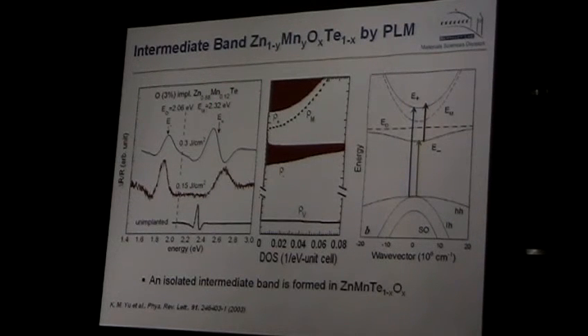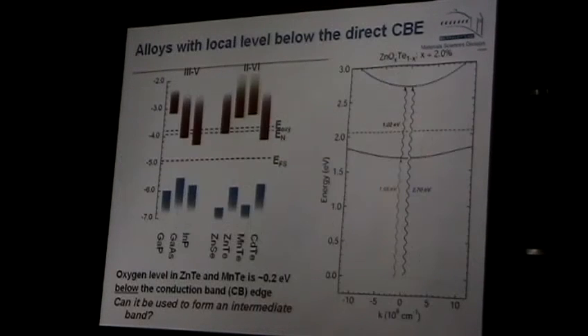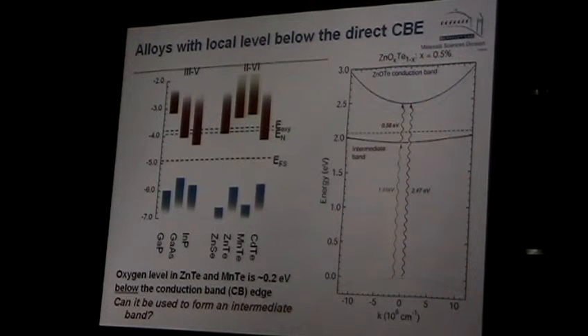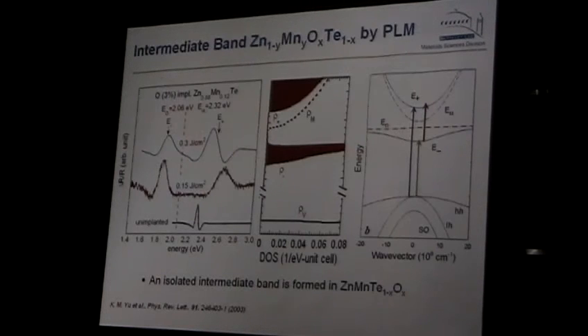Because we were afraid oxygen would escape, we put it in. So manganese was put in on purpose, and manganese doesn't change much here, because the conduction band of manganese telluride and zinc telluride is the same. So if we are adding manganese, it doesn't change much here. This distance remains almost the same. So we did this, and we implanted, in this case, probably 2% of oxygen, and used different